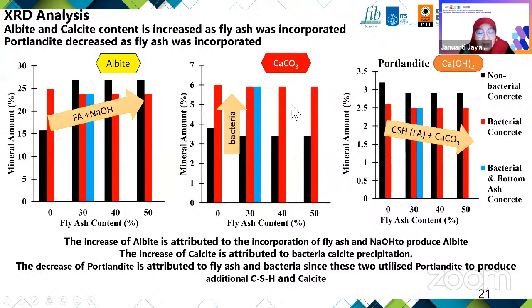On the other hand, we can see that there is a slight decrease of portlandite as a product of cement hydration. Why? Because it reacted with bacteria and silicate in fly ash to produce new calcium silicate hydrate and precipitated calcium carbonate in the concrete pores.